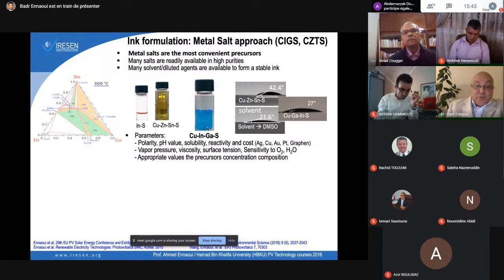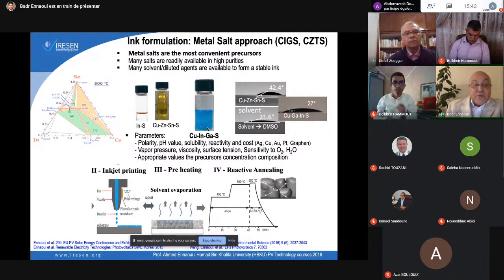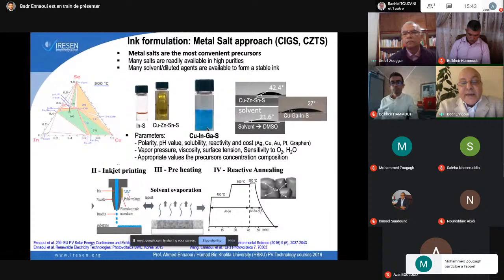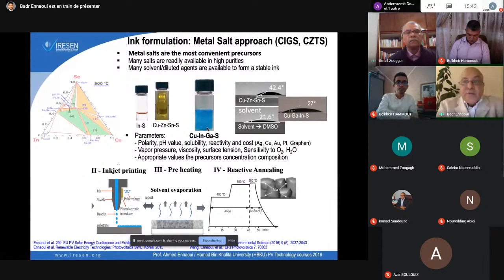We prepare ink which is stable for months. And there was a PhD work from one Chinese guy in my group. We are able to make a process which starts with ink formulation, for example, of copper indium gallium sulfide or copper zinc tin sulfide. Then a first annealing, what we call preheating, so that the solvent will evaporate. And the second annealing at high temperature, reactive, then you have to add some selenium or sulfur to get a big grain. And we also use sodium in order to improve the grain size. And we are able to make a very good solar cell with this.